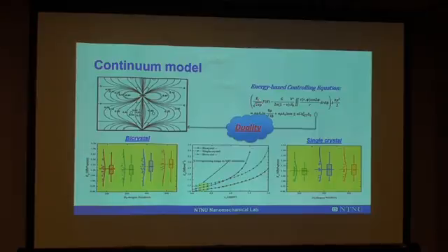The first term of the left side is the stress caused by the applied K1 field, and the second term is the stress due to the hydrogen drag. In the right side, the first 2 terms are the self-energy of dislocations, and the third one is the interaction energy between dislocations and grain boundaries. And we should notice that there is a specific sign, a positive and minus here. It reflects the dual role of the grain boundary on the dislocation emission.